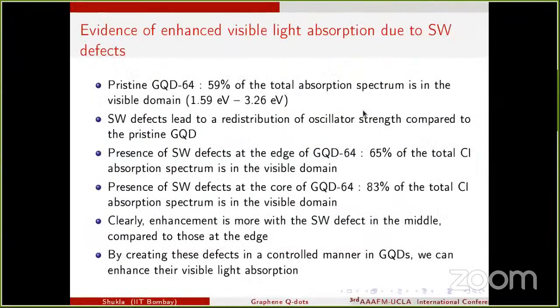I can summarize the findings for this work. For pristine quantum dots, we found that 59% of the total optical absorption is in the visible domain. But for the SW1 quantum dot, with the Stone-Wales defect at the edge, 65% of the absorption is in the visible domain. The most dramatic change occurs for the quantum dot with the Stone-Wales defect in the middle: 83% of the absorption spectrum is in the visible domain. So clearly, if one could create these Stone-Wales defects in a controlled manner, one can use them in devices where absorption is needed in the visible region of light.